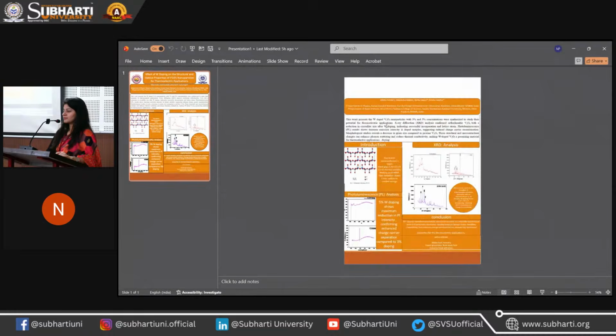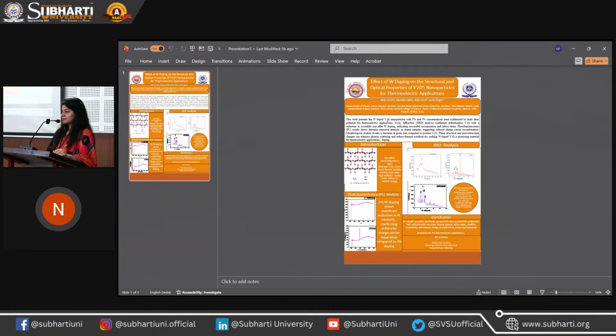X-ray diffraction analysis confirmed orthorhombic V2O5 with a reduction in crystallite size after W doping, indicating successful incorporation and lattice strain. PL results show decreased emission intensity in doped samples, suggesting reduced charge carrier recombination. Morphology studies reveal a decrease in grain size compared to pristine V2O5.